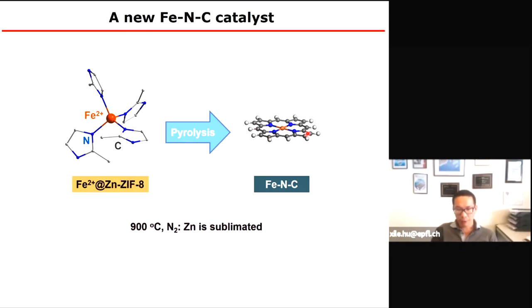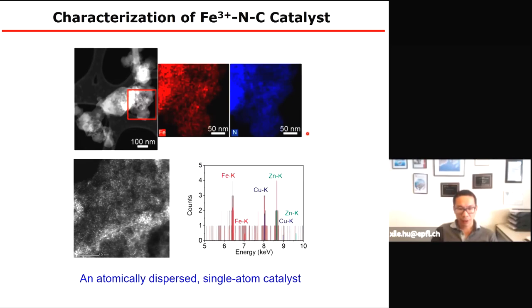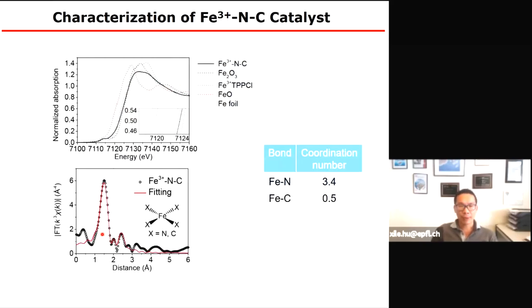Now, we characterized these compounds, and we found that indeed they are atomically dispersed, which you can look at in various ways. This is an aberration-corrected TEM image. We can see single atom species, which is consistent with this. We then characterized them by X-ray absorption spectroscopy. We can look at the edge energies and the oxidation states. We can also look at the structures, so we know it's iron 3 to start with. It has about 3 nitrogen and 1 carbon, similar to many such species in the literature, except that for iron compounds, typically they have iron 2.